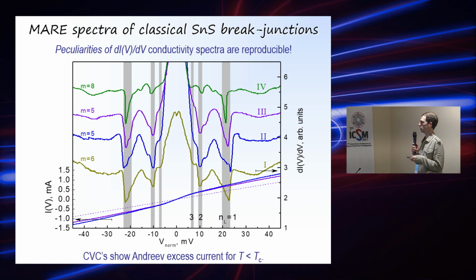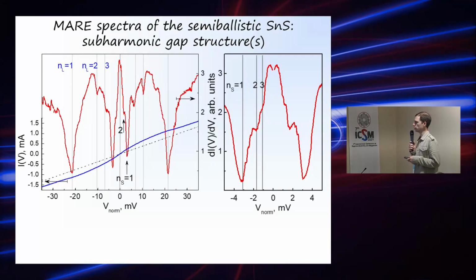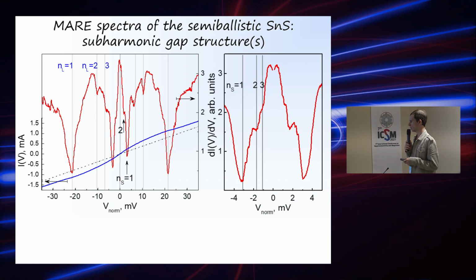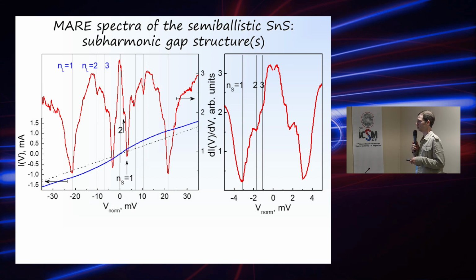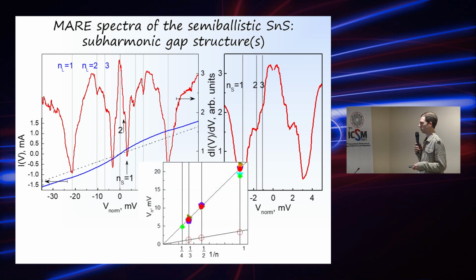We could see that spectra are reproducible, and so if we take another sample of this neodymium 1111 compound and one of the spectra, where the background is already suppressed to enlarge the main peculiarities, the Andreev minima, we could see some series 1, 2, 3 probably for the large gap, and we could plot this data for this contact, it's red points, and for other contacts here, because we know this formula. So if we plot its position as inverted n number, it should be a line going to the origin.